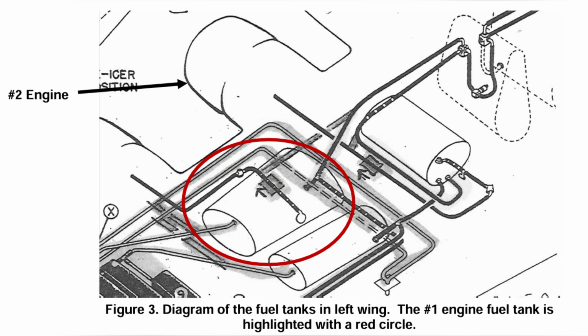Records showed that a fuel leak in the number 1 main tank had been evaluated and repaired shortly before the accident flight. The key question was whether that repair had actually sealed the crack or merely covered a failure that was still progressing. The decisive evidence would have to come from controlled examination of the recovered repair hardware. The causality question therefore moved from wreckage reconstruction to the recovered number 1 fuel tank pieces and the repair area documented in the maintenance history.